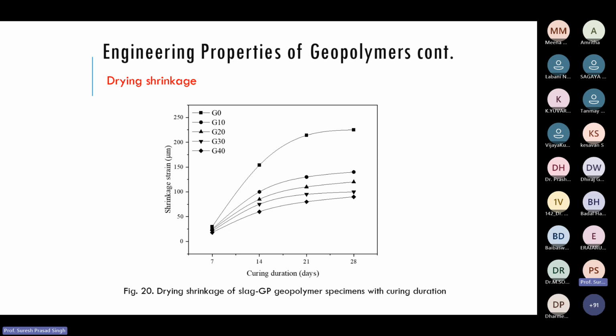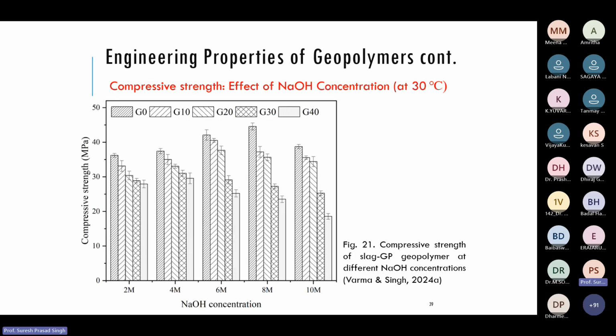What are the benefits you are getting out of this? And then the compressive strength, with different molarities and different glass content. But as you see here, you can notice that if you replace the slag by glass powder, the strength reduces continuously. This happens with normal curing. Normal curing means an ambient condition between 20 to 30.